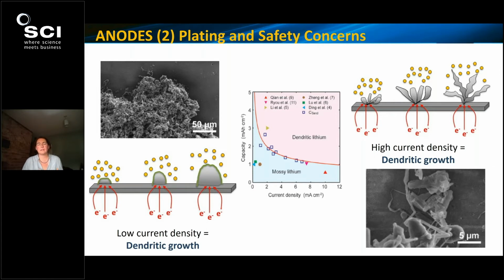Another significant mode of aging in anodes is lithium plating, which can have associated safety concerns. And this has a lot to do with the magnitude of the current that is experienced by the anodes.